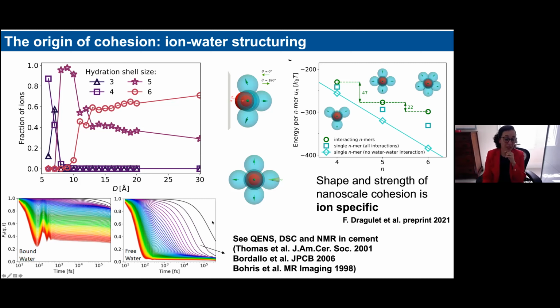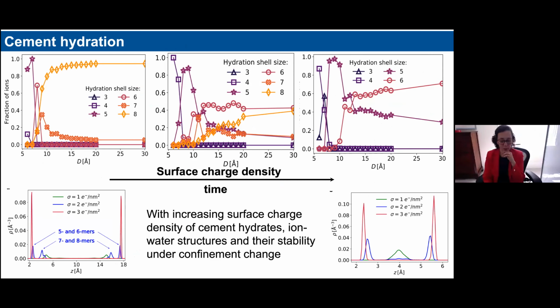And so you can see that there is a population that they call free water, and a population of water that you call bound water, that you can clearly distinguish from the dynamics. So in this type of simulation, we can actually compute the dynamics of the water for different degrees of confinement. And so we can create this direct connection with the experimental observation that basically confirms that what we see is relevant to what happens in the real material.